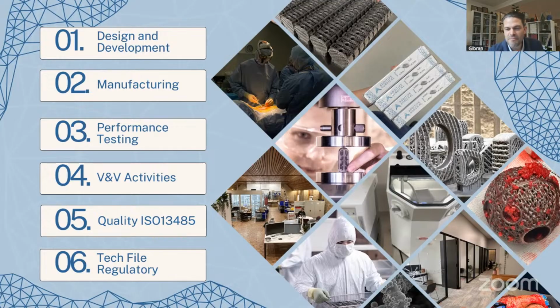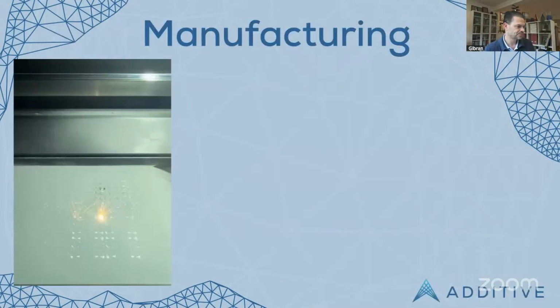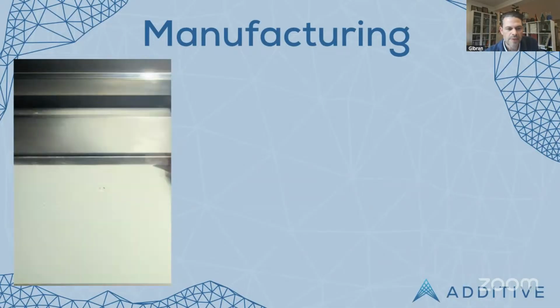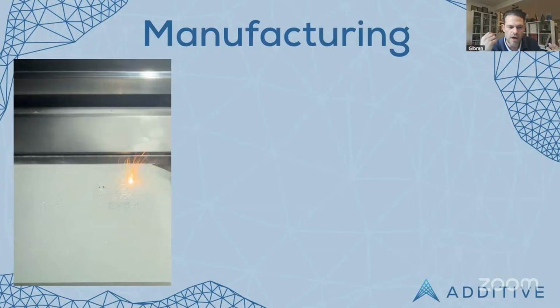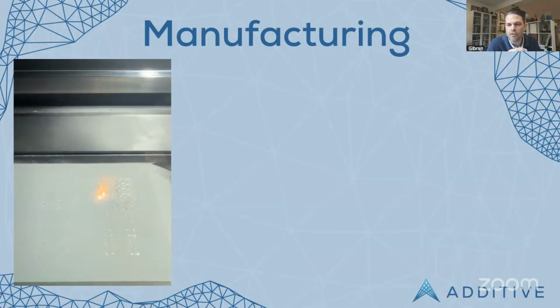Now, I want to show you the manufacturing process quickly in a couple of videos of our 3D printed titanium implants. So you can see the video here where there's a laser that is literally melting a very thin layer of titanium powder. A blade will come across and deposit a few microns of titanium powder over the implant bed. The laser then comes back on and melts each layer. So it's about 8,000 layers. It takes overnight to print. And at the end of it, you get a small cube of a bed of implants.